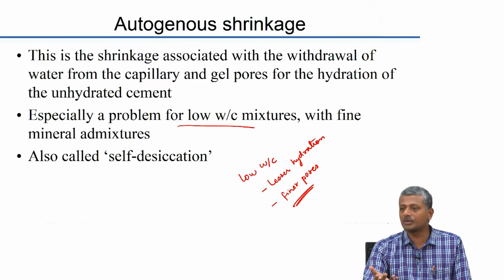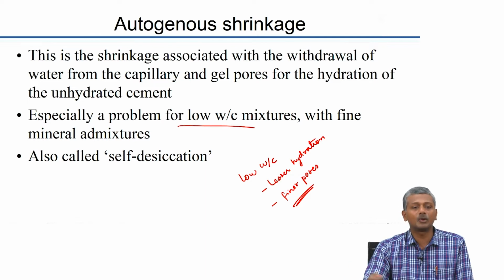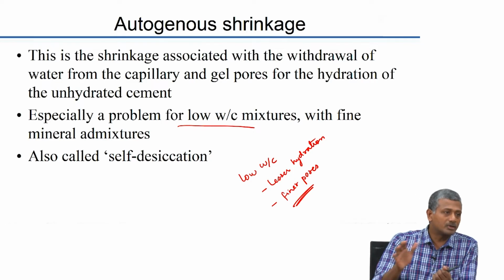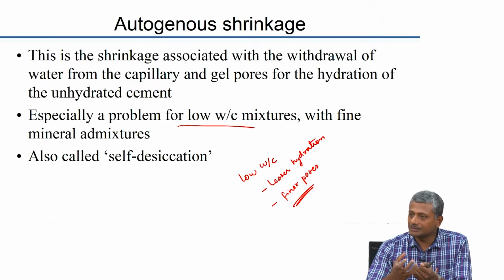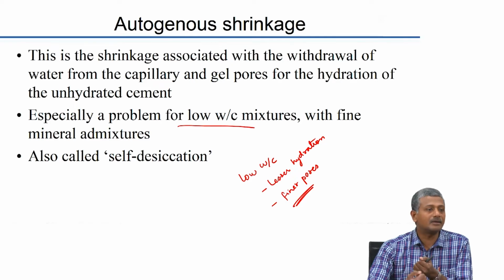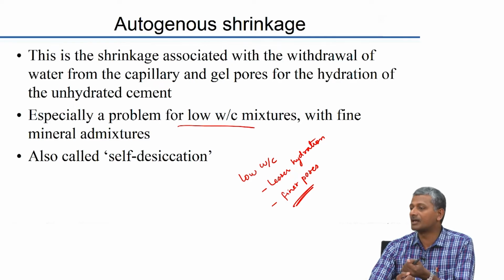So, let us think about a curing situation in which you start membrane curing. Okay. When you do membrane curing of concrete, there is no external water that you are providing from the outside. So, again the strains generated because of movement of water to hydrate the unhydrated parts of the cement is going to be significantly high.